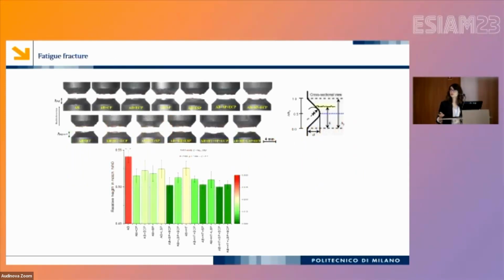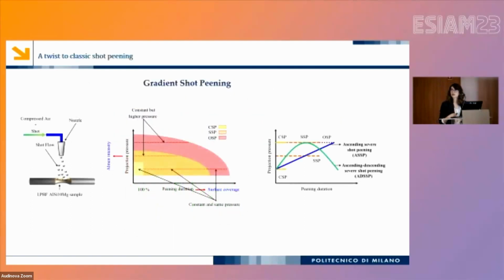One interesting observation was that we normally would expect the failure to happen at the notch root, but in all these samples, especially in the as-built sample, we always had the fracture section on the down-facing area, where we had the highest surface roughness in our samples. As we applied these treatments, we were able to displace the fracture section to the critical notch root. And here, as we quantified this distance, you can see that the hybrid treatments were able to bring the fracture surface to the critical area.